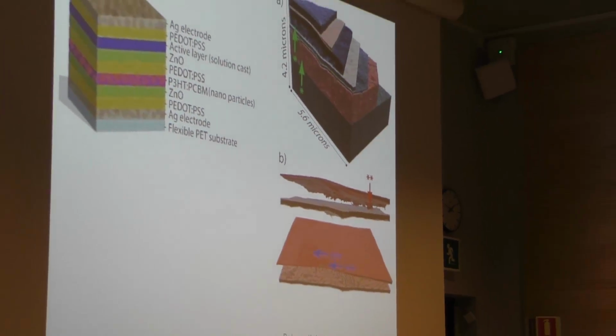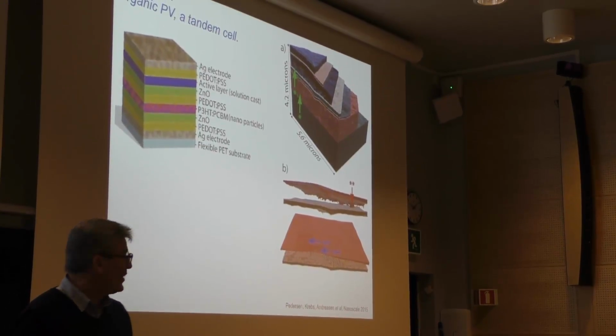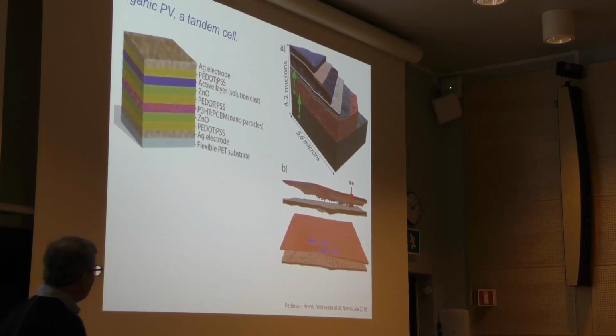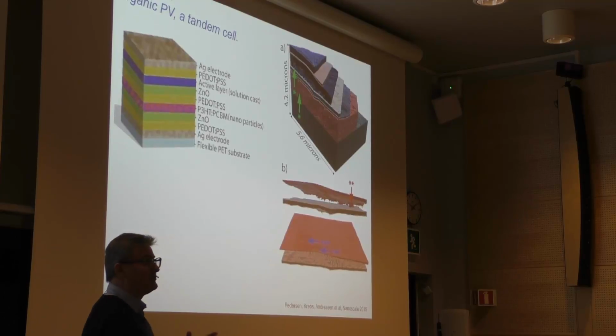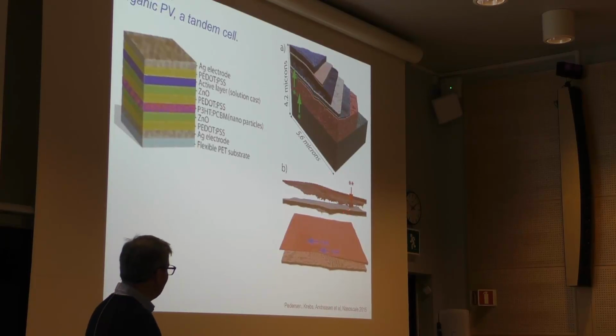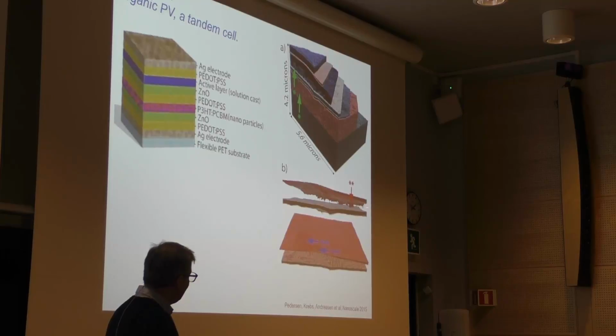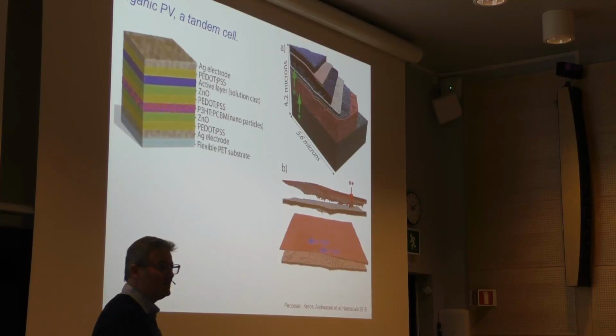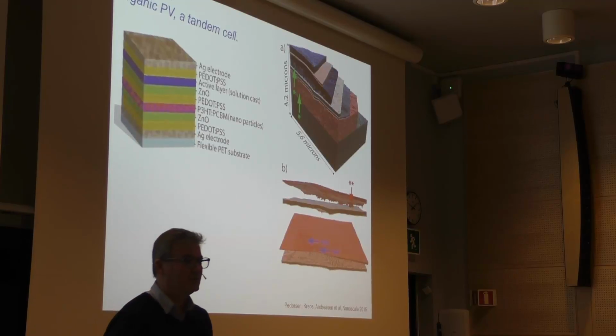And one nice thing about that was also that we were able to identify short circuits here, which explains why the performance of this particular solar cell was quite poor. I don't have the numbers here, but this was also repeated with a different stack where additional efforts were made to avoid this kind of short circuits across insulating layers that is shown here.